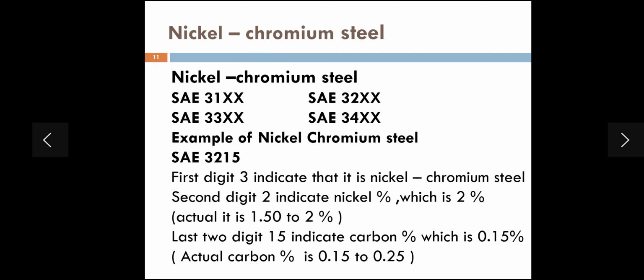So next is nickel chromium steel. SA31, SA32, SA33, SA34, these are nickel chromium steel grades. One example of this steel is SAE 3215. The first digit 3 indicates that this is a nickel chromium steel. The second digit 2 indicates the principal element percentage in the steel, so it is the nickel percentage, 2% of nickel. And the last two digits 15 are the carbon percentage in the steel, 0.15%.